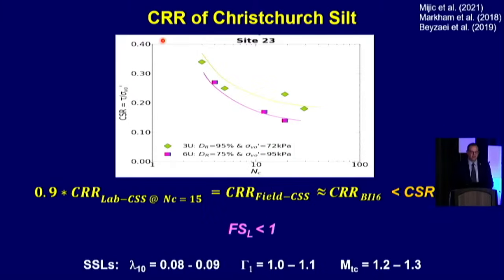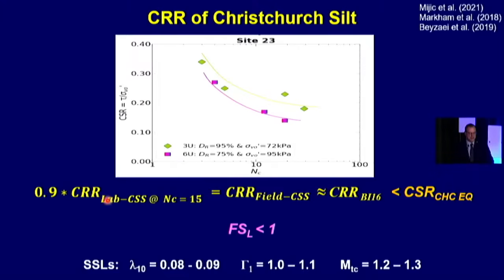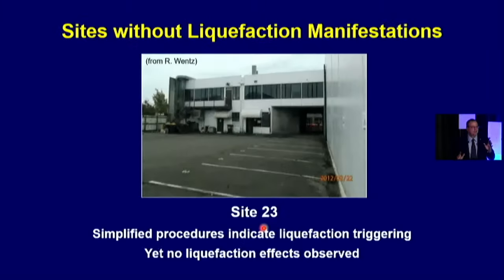When we look at the cyclic resistance ratio of the Christchurch silt, this is that silt material at a relative density of 75%. This is at a relative density of 95%. And so we're seeing things that make sense in terms of sand-like behavior. If we take the cyclic resistance ratio from the lab test, we adjust it so that we get the field value. It's very similar to what most of the methods calculate from the CPT. And both of those values are well short, much less than the demand. And so these soils liquefied, but yet we have no manifestations of liquefaction. So we're going to have to explain that.